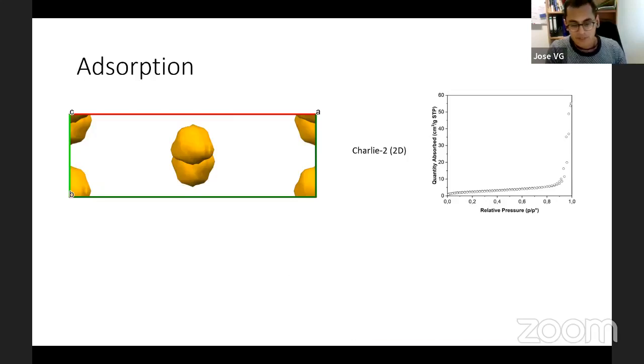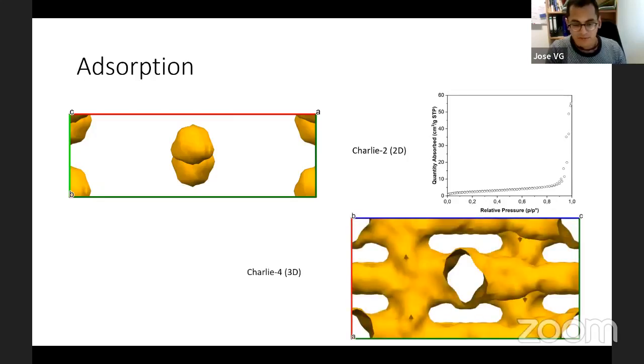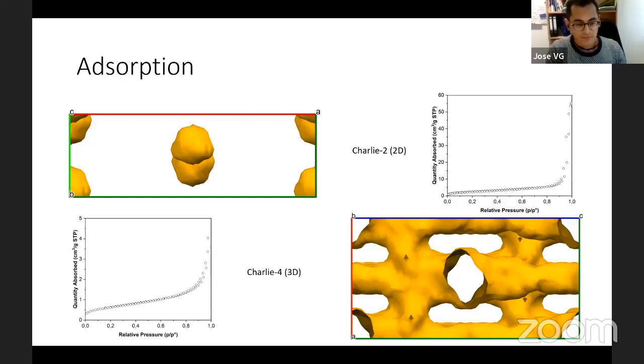Although we were expecting to have very large channels in Charlie 4, which is more like a 3D structure, we didn't observe, or we observed an even worse adsorption in Charlie 4. The reason for that is because some of the ligand, in this case some 2-methylimidazole, is trapped inside of the channels. So that blockades the channels and makes them not useful.